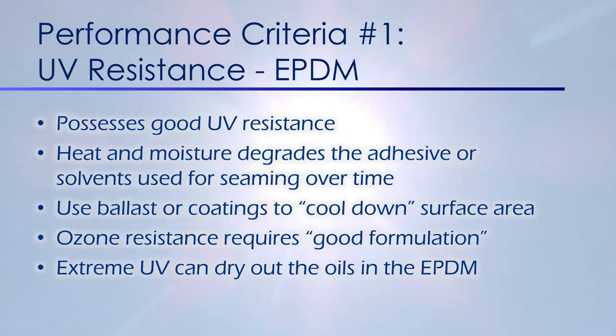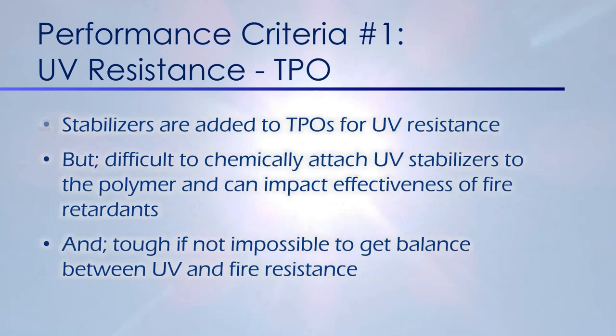be reapplied over time. So sometimes you can use a ballast or a coating to cool down the surface of that roof, but it does break down over time, and it can really dry out those oils in the EPDM. So if you have an EPDM roof that is not ballasted, you run a greater chance of drying out those oils and causing earlier failure on the roof.